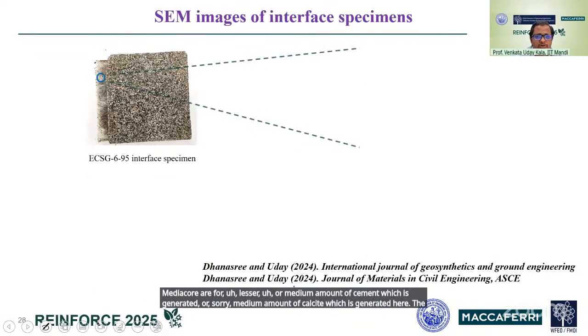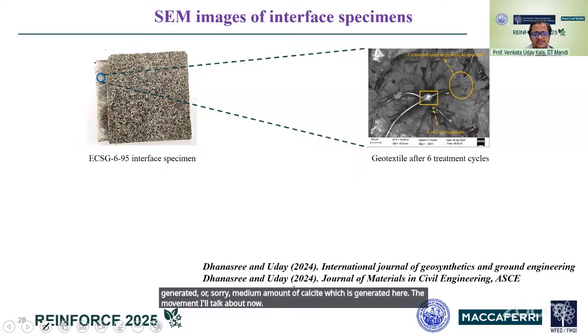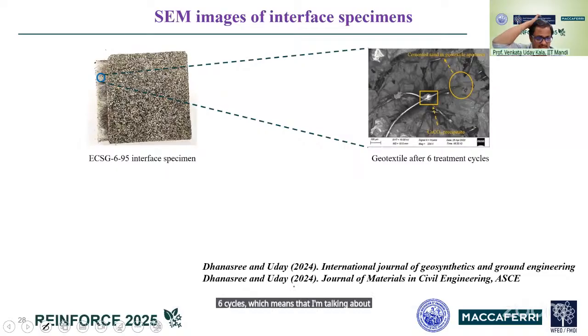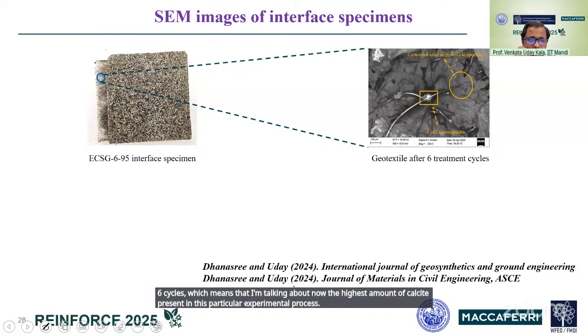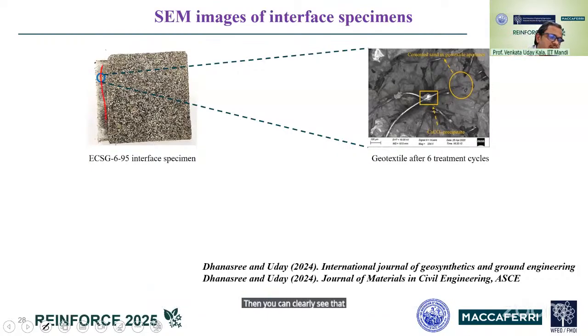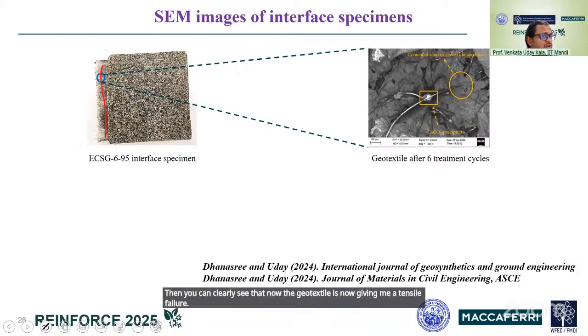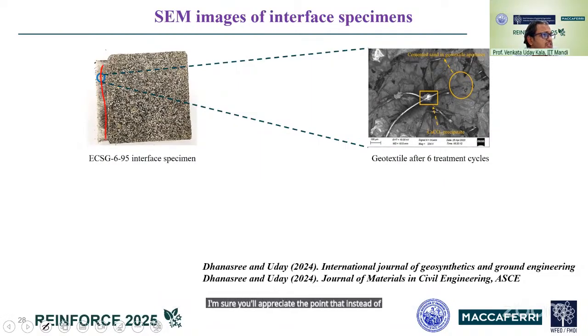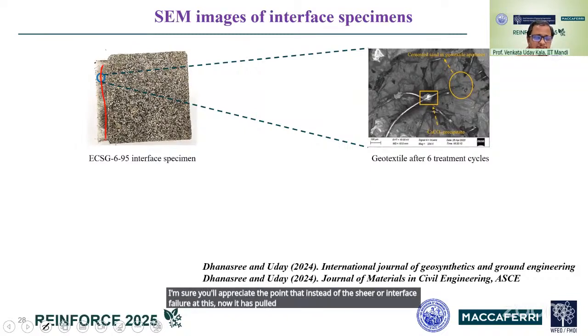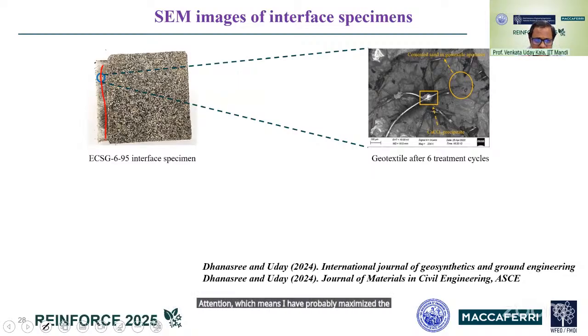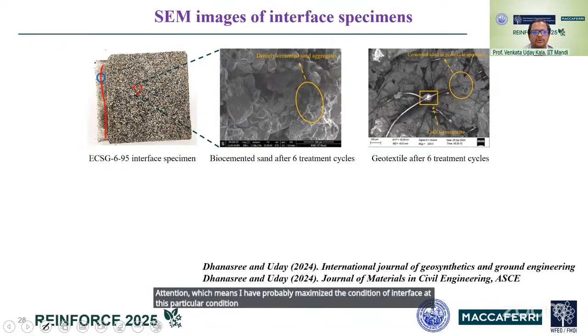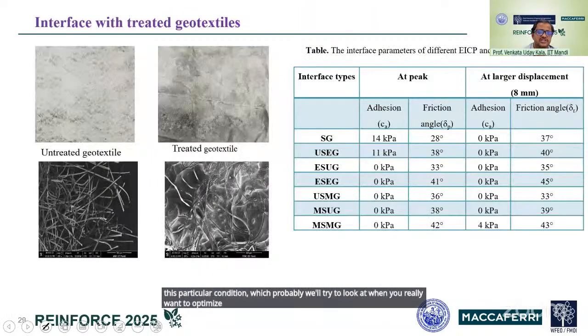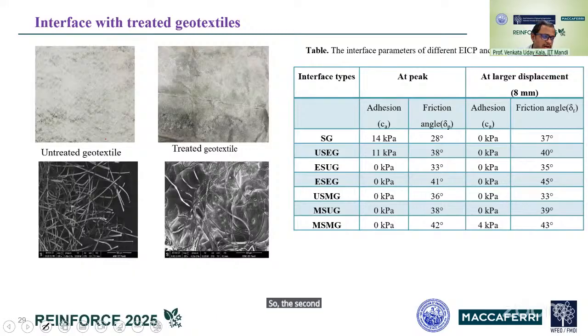The moment I talk about 6 cycles, which means I'm talking about the highest amount of calcite present in this particular experimental process, then you can clearly see that the geotextile is now giving me a tensile failure. I'm sure you'll appreciate the point that instead of the shear or interface failure, it has now pulled the geotextile to fail up to the extent of tension, which means I have probably maximized the condition of interface at this particular condition, which we'll try to look at when you really want to optimize the conditions.